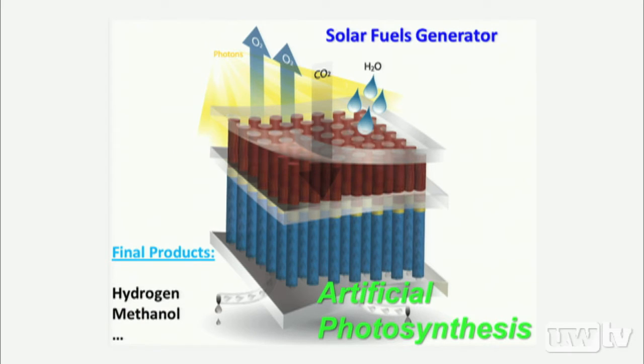But in this design, we have a high surface area semiconductor nanowire array on the top, that is our photoanode. When the water comes in, that's where the water oxidation will be happening. And this high surface area semiconductor anode will be decorated by water oxidation catalyst. So there will be an interface between the nanowire and oxidation catalyst. And in the bottom, that's the photocathode. Photocathode is where the water reduction or CO2 reduction will be happening. So that's going to be another small bandgap semiconductor. It's high surface area. It will be decorated by water reduction or CO2 reduction catalyst. So ultimately, the product will be hydrogen and or methanol.